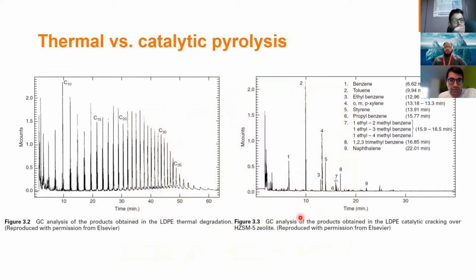If you look at the contrasting picture of the same pyrolysis process for low density polyethylene, on this side you see the thermal degradation product, so the oil of LDPE thermally degraded, and pyrolysis oil of LDPE in the same conditions but with a catalyst. You can immediately see that the range of hydrocarbons in thermal pyrolysis is huge. So you get lots of different compounds in a thermal pyrolysis. But on the other hand, when you use a catalyst, you can actually tune the product, and you get a very narrow band of compounds, which is very useful for the next step of purification. And you get what you want. But in this one, you get a lot of different types of unnecessary compounds.